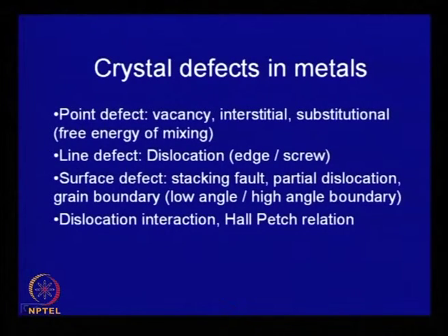And we also calculated that if the crystal is perfect, it does not have any defect. In that case, the stress required to cause slip in a crystal is very high, but in reality the metals deform at a stress much lower than the ideal resolved shear stress. And the reason for this lies in the fact that crystals are never perfect, they have defects, and in this chapter we shall learn about the types of defects which are present in metal crystals, and what is their effect on properties.